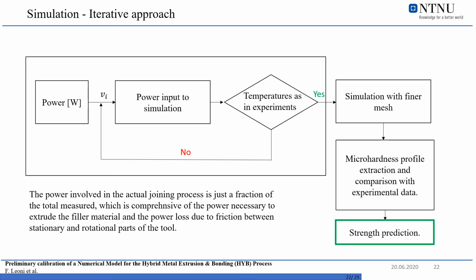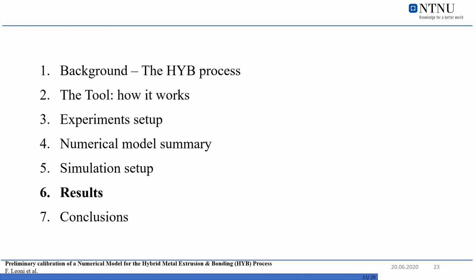An iterative approach was used in order to find out the actual heat input to give to the simulation to get the best fit with the experiments in the thermal field, and so to get the best possible prediction in the strength of the material. Let's see some of the results.